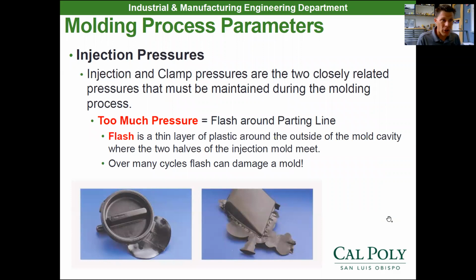Now, the pressure. If we go ahead and just max out the machine on injection pressure, we're going to get flash around the parting line. So flash is a thin layer of plastic that went outside the mold cavity where the 2 halves of that injection mold meet. So you can actually ruin a mold if you flash over many different cycles. Over time, it starts to flex the mold or wear the mold out where the plastic is leaking out of the mold. So you can actually hurt a mold by flashing it too many times over time.